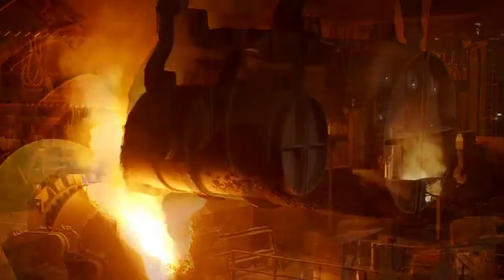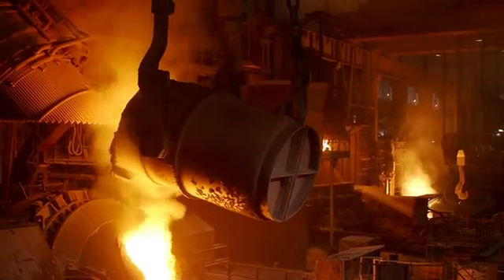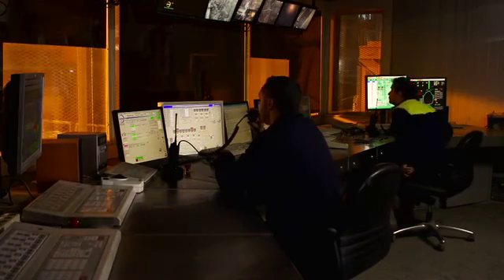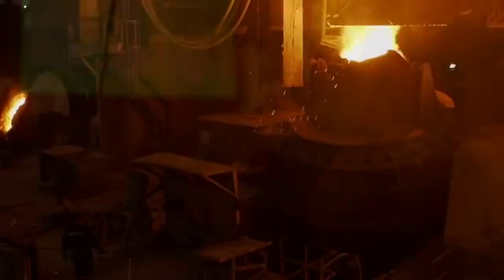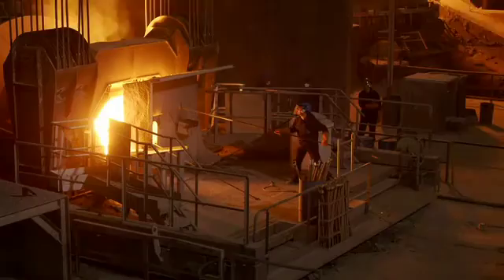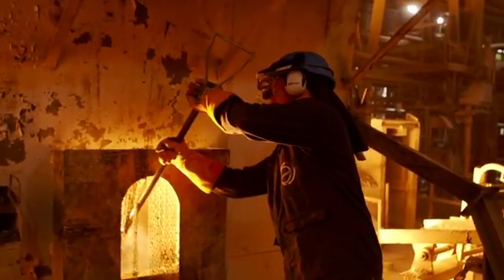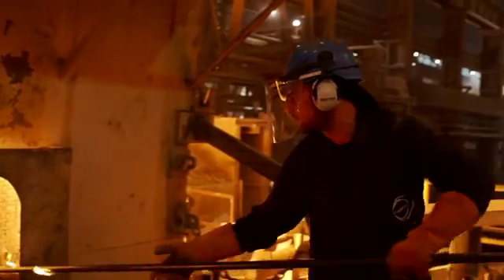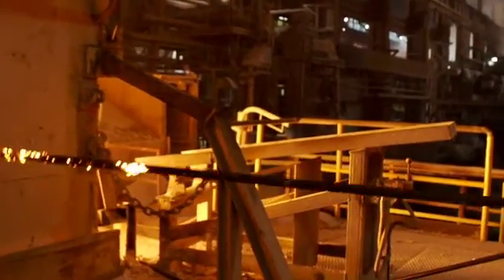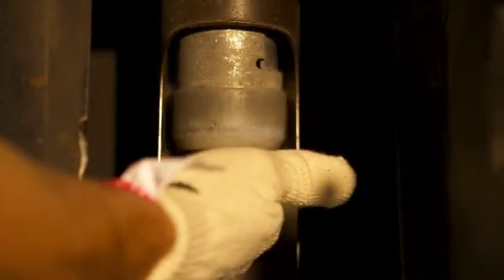This phase starts with a blast of oxygen and inert gas and finishes with the refining of the alloy. The main process steps in the AOD are: decarburation, where the carbon content of the melt is minimized; reduction, recovering metal from the metallic oxides; and desulphurization, where the sulfur content is reduced. In the final stage, small additions of high-quality raw material can be made.